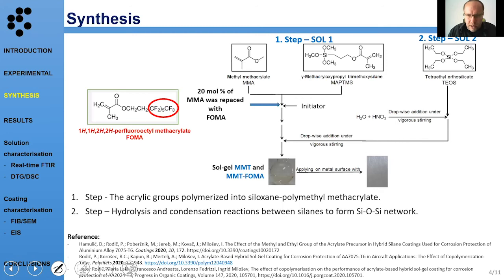So here is the synthesis. The flow chart of this solution preparation consists of 2 sols. The first sol contains the organically modified silane precursor, which is combined with methyl methacrylate and, in the presence of an initiator, polymerized together to get the final solution. For this presentation, we also replaced 20% of the methyl methacrylate with perfluorooctyl methacrylate. The reason is that we want to figure out what the effect of this perfluoro group is in the synthesis of this sol gel coating. This is sol 1, so here we will mainly focus on copolymerization.